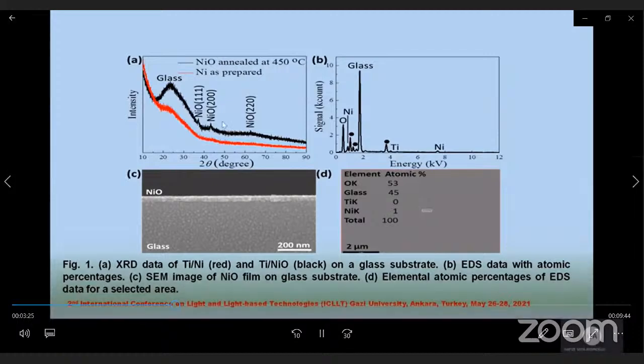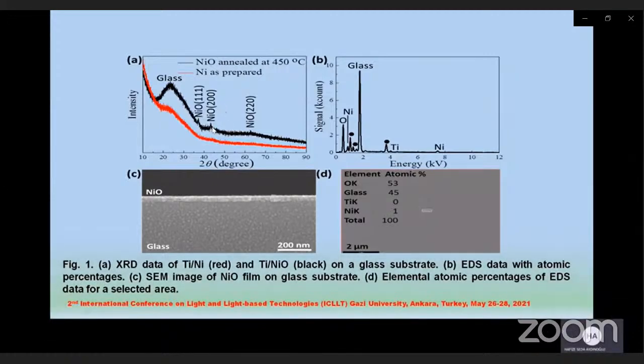The formation of nickel oxide, black line, appears with major peaks after annealing the sample at 450 degrees centigrade for 2.5 hours in air. Three major peaks of the nickel oxide sample were observed at 2 theta equals 37.3 degrees, 43.3 degrees, and 62.7 degrees that correspond to the crystal planes of 111, 200 and 220 respectively.